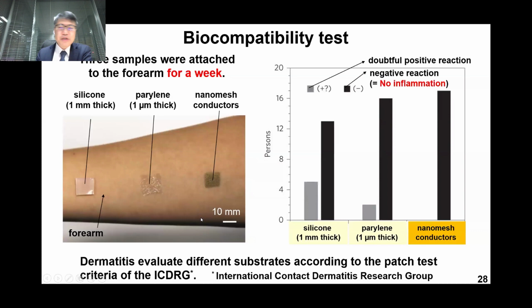Such breathability is quite important to ensure biocompatibility. Indeed, when the nanomesh conductors were attached on the surface of people's forearms continuously for a week, none of the participants showed doubtful inflammatory issues. But when 1 micron thick parylene and 1 millimeter thick silicone were attached on the surface of the forearm for a week, they exhibited a fairly high risk of inflammatory issues. So in that way, we prove that breathability is quite important for biocompatibility.